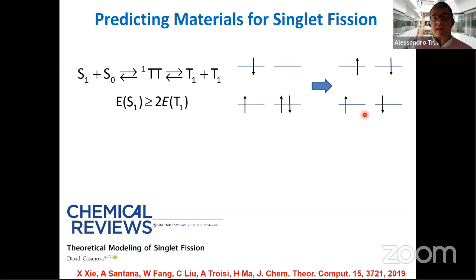because the energy is such that this is energy favorable. So the energy of the triplet is less than half the energy of the singlet. This process is spin allowed if the electrons are correctly aligned. And it's very interesting because you can generate 2 excitons from 1 photon. Therefore, you can create a solar cell with higher efficiency, and this has been proved. Lots of theoretical interest in this topic, so there is a review if you're interested in it, but a lot of interest from people trying to design materials for singlet fission.